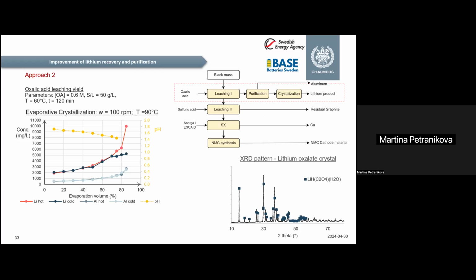Because lithium and aluminum are quite different elements, that helps the separation. So then she also tried evaporative crystallization, and with the conditions she tested, she very effectively separated lithium from the aluminum. It is also still research which we have been working on, and we will continue using different approaches to get good separation of the lithium and aluminum. But still, already with this step, we have separated all the lithium from the system, while copper and transition metals stayed in the solid form.